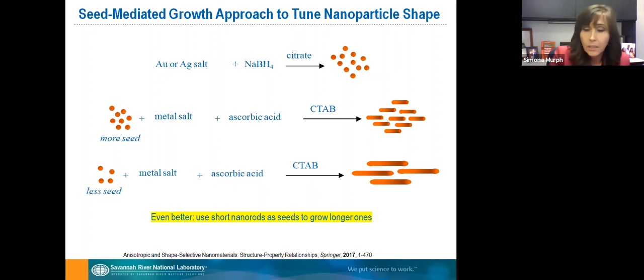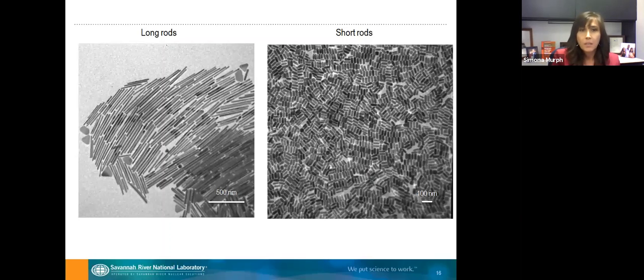You can get these rods up to 500 nanometers in length with a diameter pretty constant around 20 nanometers. So you can see here the long rods, around 500 nanometers, so we can tune the length of these rods, but you can also see on the right the short rods. Of course, at the beginning it was not the most monodispersed system, so we always had to go through all kinds of steps to separate the spheres or other shapes from these rod-like nanostructures.